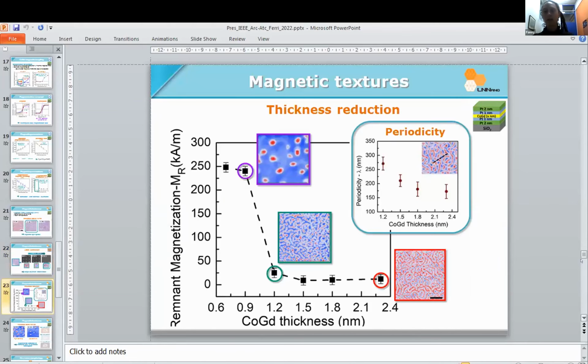Now, coming back to the unpatterned thin film. Here the graph shows the remanent magnetization as a function of the thickness. In red is the thicker system that I showed, with the spin spiral. You can see in the inset the periodicity of the spin spiral, which increases when we decrease the thickness. So as a function of thickness, we can already see some modification of the energy inside our system. The periodicity increases until, at 1.2 nanometers, the spin texture is more like a mix. You don't have a clear spin spiral.